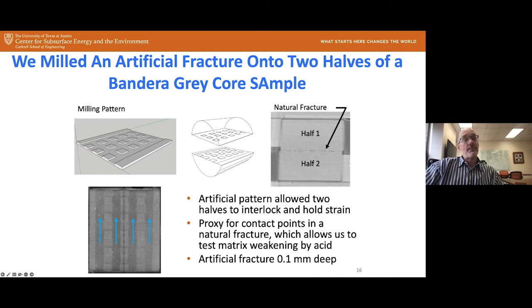If you look at this CT image here, each little square here represents one of these raised asperities. One comes from the bottom part of the core and the other comes from the top part of the core, and so they alternate in this pattern. And then in between we had these flow channels that were about 0.1 millimeters deep, and so you got more brine flow through these flow channels, and then it could diffuse, or if there is advection through the actual sandstone itself, or these asperities where flow somewhat through there.